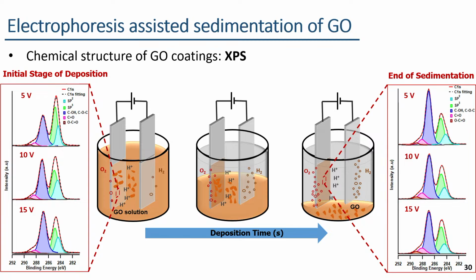So, when comparing both coatings obtained at the initial stage of deposition and at the end of the sedimentation process at 15 volts, they do not show any variation in the total amount of basal plane oxygen functionalities. Basically, these two coatings show the same amount of basal plane oxygen functionalities. So, during the EPD process, the smaller GO particles with a smaller amount of oxygen functionalities get deposited on the anode at first, and then the larger particles with a high amount of oxygen functionalities get deposited on the anode later.